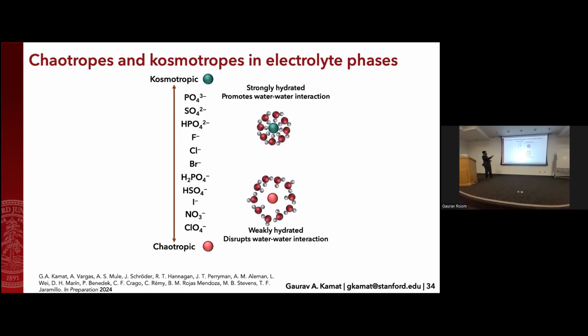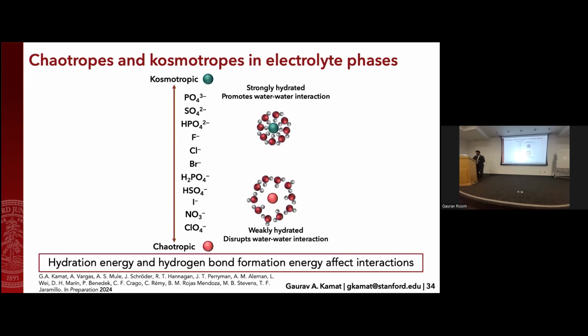Compare that to something like phosphate or sulfate, which are doubly or triply charged. You now have much stronger hydration, and these actually promote water-water interaction. And it turns out that this is quite important for the hydration energy and the hydrogen bond formation, because that is something that happens near your surface that affects your catalyst environment interactions.